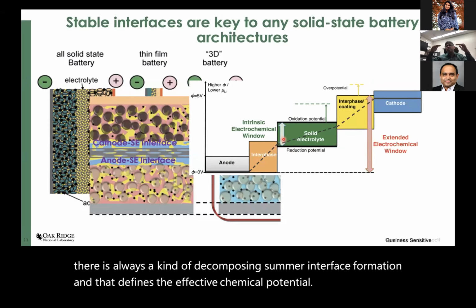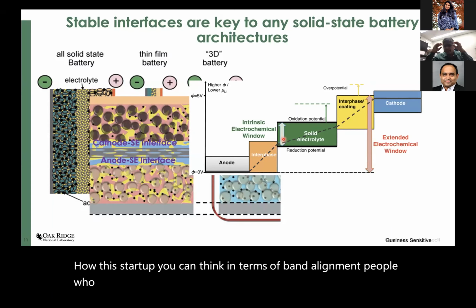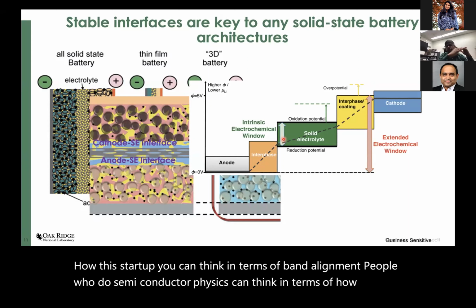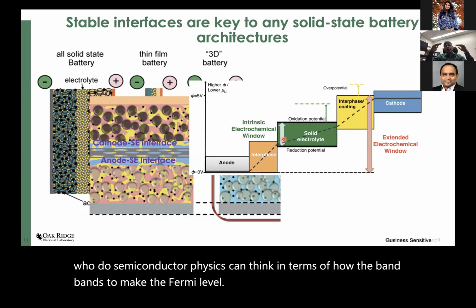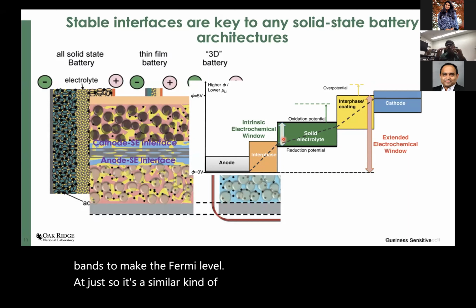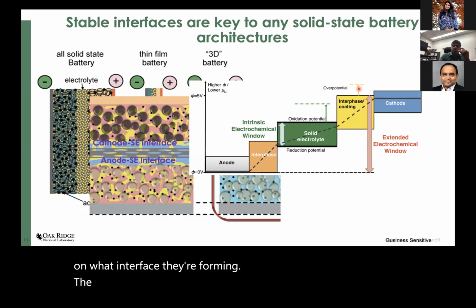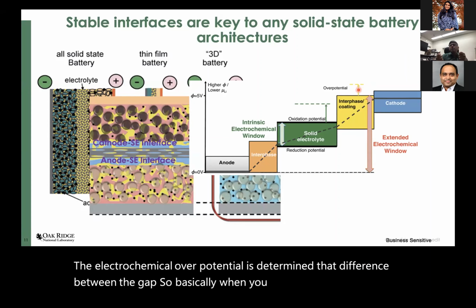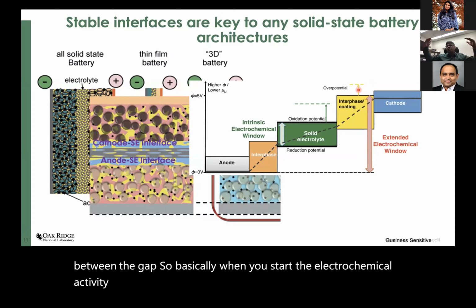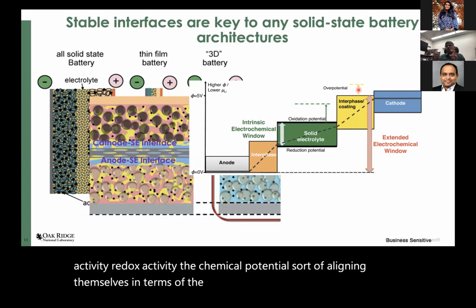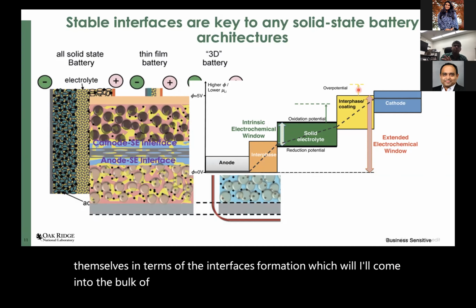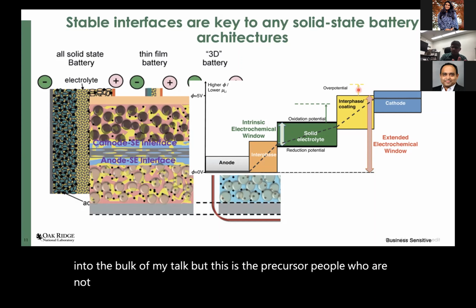How this sort of, you can think in terms of band alignment. People who do semiconductor physics can think in terms of how the band bends to make the Fermi level adjust. So it's a similar kind of thing, which definitely, depending on what interface they're forming, the electrochemical overpotential is determined by the difference between the bands. So basically, when you start electrochemical activity, redox activity, the chemical potentials sort of align themselves in terms of the interface formation, which I'll come to in the bulk of my talk. But this is the precursor. People who are not doing solid state batteries and things, this is a kind of precursor for them.